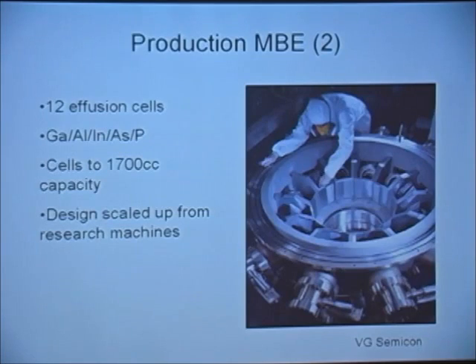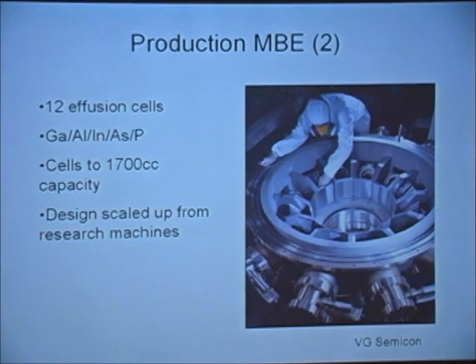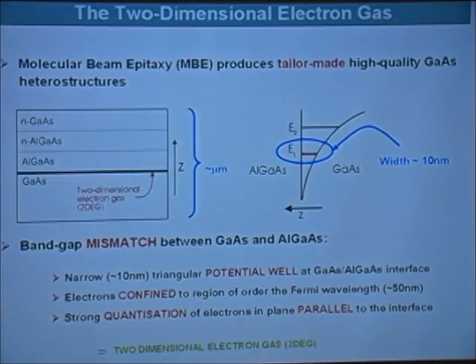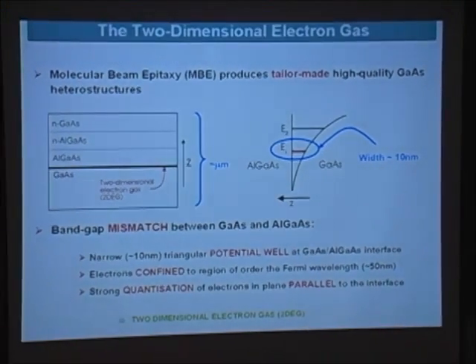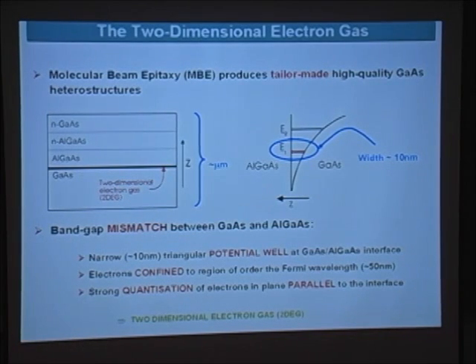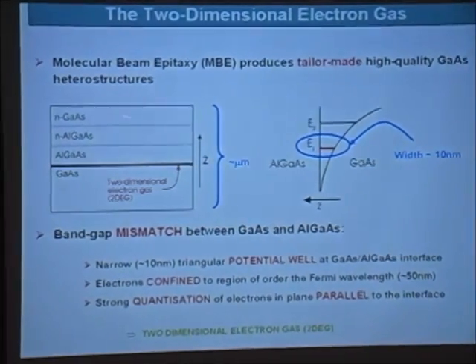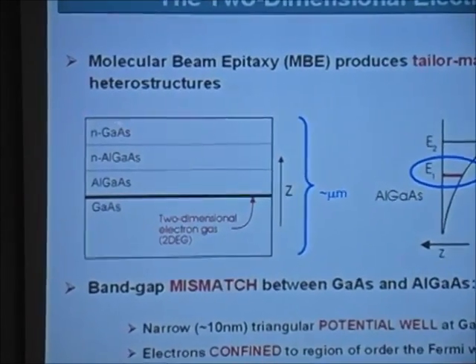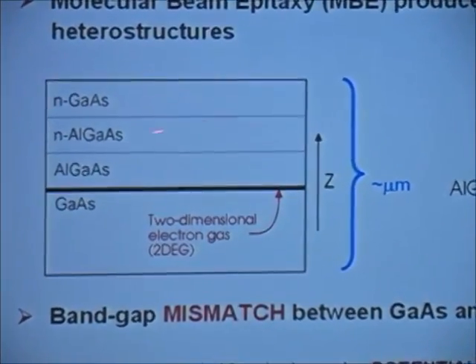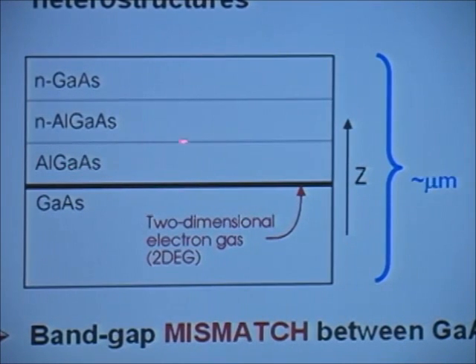It's actually really where the semiconductor wafers are loaded, and then the layers are formed on top of them, and they're taken away to be diced up and fabricated. The two-dimensional electron gas can be made from this particular technology, and I don't want to dwell upon it too much, but what it looks like is this. There we have a layer of N-type gallium arsenide on the surface. That is doped, actually. It forms a sort of protective layer or gate. You're familiar with gates from MOS type of transistors. Can be doped. And there's the aluminium gallium arsenide. And there's the gallium arsenide.